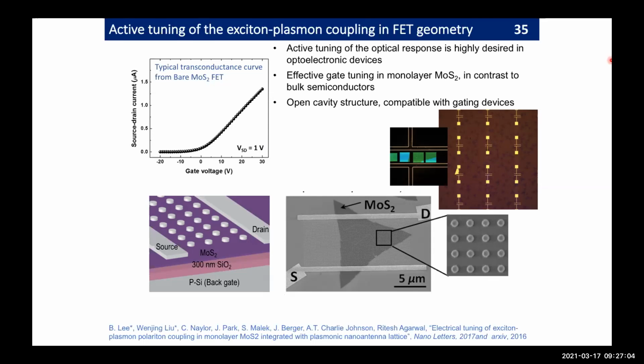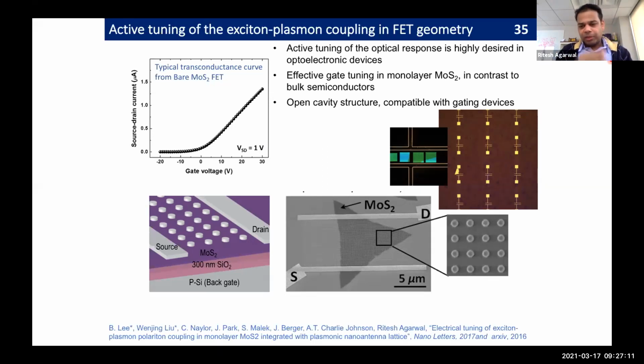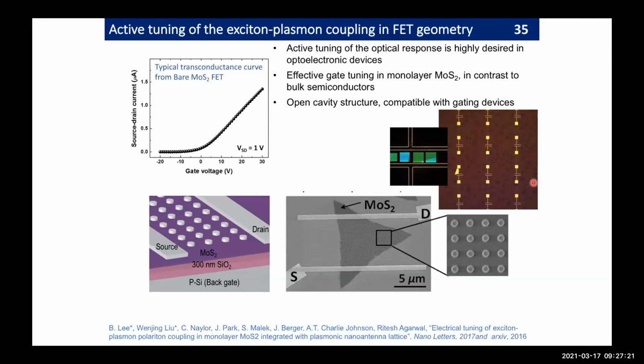Thank you. And the reason why we don't put these 2D materials on top of the pre-patterned lattice is because of the strain effects. You can create large strains, and that changes the resonances of these 2D materials. So this is the reason why we pattern on top. Okay, sure. Thank you.